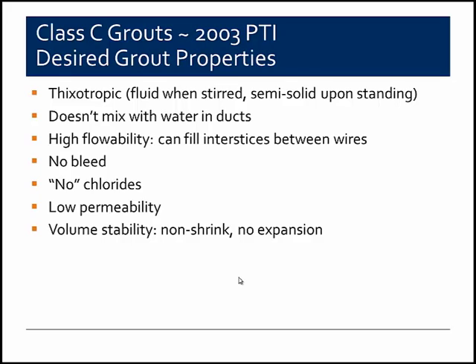and so that's actually a good thing. They do have a very high flowability when they're still being mixed or stirred, and it does a very good job of filling the interstices between those individual wires on the strands. They have very low or no bleed, so that's bleed water, which is very common in concrete or cementitious products. They're not supposed to have any chlorides. They have very low permeability, and they're very stable from a volume standpoint. They don't shrink and they don't expand, and so very good properties from a grouting standpoint.